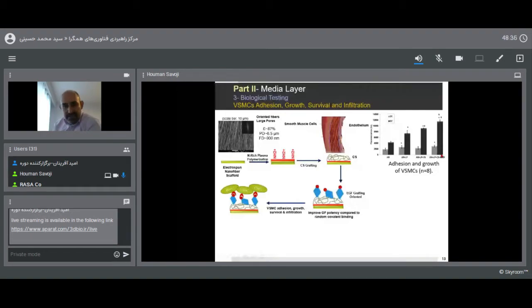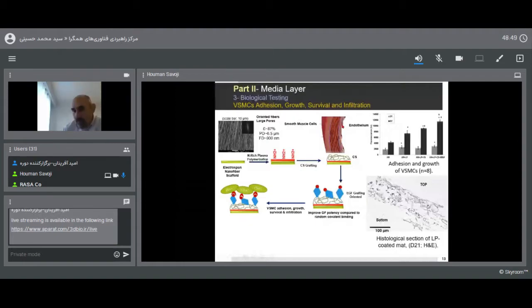The only difference here is that we made fibers with a larger pore diameter. This was intentional because in the medial layer, the cells should infiltrate inside the scaffold. In this histology image, you can see that the cells really infiltrate and penetrate inside the scaffold. Since you have the large pore size, the bioactive coating, including the plasma, chondroitin sulfate, and the growth factor, can penetrate inside the scaffold, and the cells follow them and also go inside the pores. And so this was really the summary of this project.